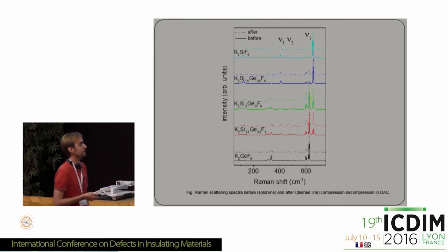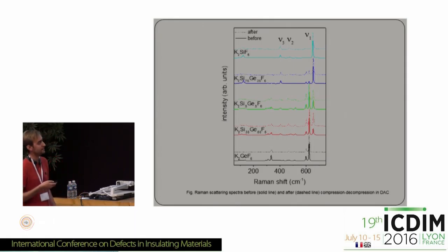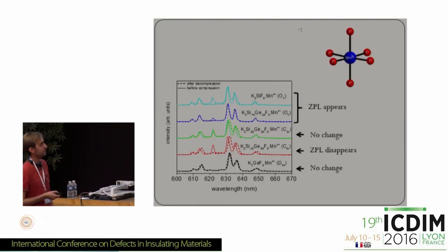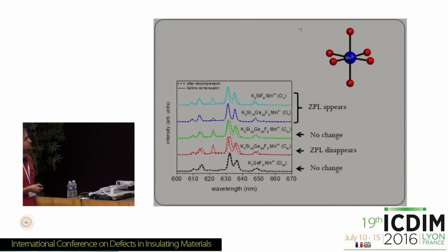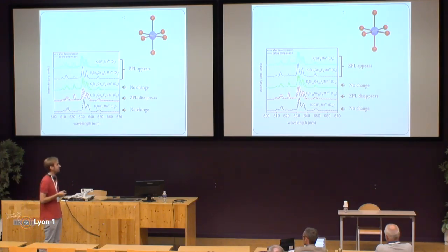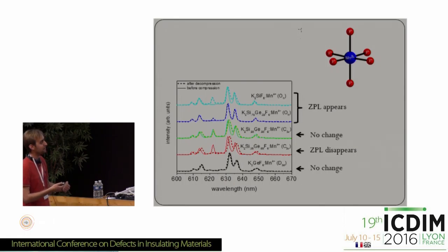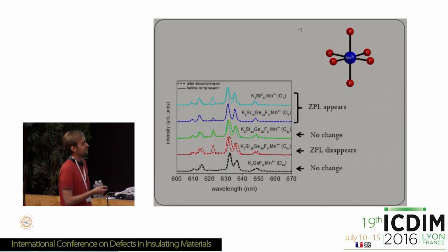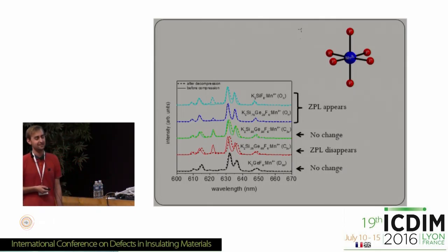The bottom line is that there actually is no phase transition as such. The change in emission spectra is related just to a local change of the manganese 4+ site without changing the rest of the crystal. For two samples, the local symmetry of manganese 4+ deteriorated and was broken. More interestingly, by applying pressure to another sample, we actually increased the local symmetry of the dopant — which is a less intuitive result.